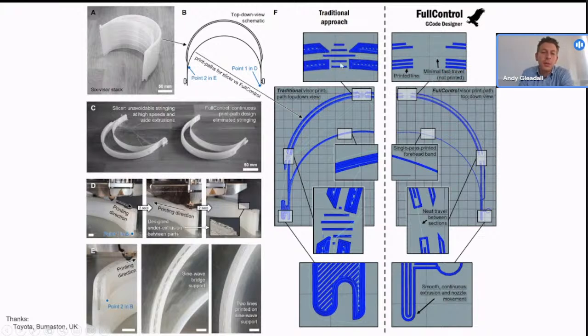The default one that you get from a slicing software has the multiple passes around the perimeter, and then the strange zigzag infill, lots of little travel lines as the nozzle is moving between the front and back sections. And this was a nightmare for the workers at Toyota to actually clean up. They were having to scrape out lots of bits from inside the gap where the actual visor was going, and it was taking them maybe 10 to 30 minutes per mask to clean them up sometimes.